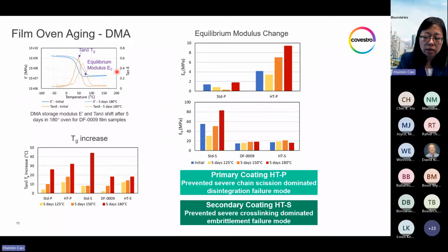Here is how we characterize the thermal property change with the aging. It is characterized by DMA by looking at the equilibrium modulus change, which represents the cross-link density of the material, and the tan delta represents the glass transition. For the primary coating, the standard coating modulus goes down as expected to almost 0 before it goes up. And the high temperature coating started higher already. It comes down a little bit, but far from being at risk of disintegration. It's still a very nice solid coating.